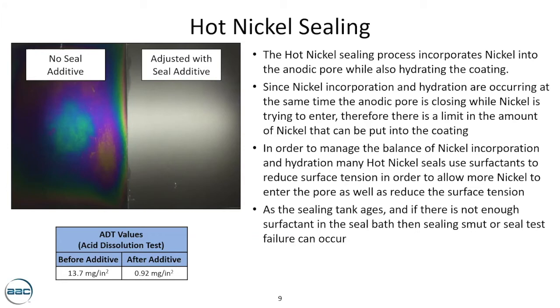So again, the big takeaway here is the surfactant management is absolutely critical. And one of the indicators I like to look at to know if I have enough surfactant in that bath is a water break test. The same logic will apply on the mid-temp seal when we go there. That's usually an indicator of whether we have enough of the appropriate chemistry proportions, and a water break is a good metric for that.